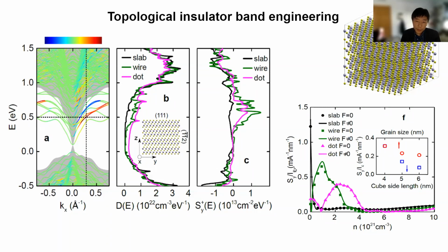And we can plot the ratio of these two, which gives us a figure of merit of how efficiently this material is able to produce spin polarization for a given charge current. Here you see a survey of this figure of merit for different carrier density and different dimensionality. We have the slab, which is this black curve, followed by the wire, and then the dot. For each of these cases, there is an optimal figure of merit at some carrier density. That carrier density can be engineered in the experiment, and we also see a dependence on the size of this quantum dot. As we decrease the grain size, we see an enhancement in this figure of merit.